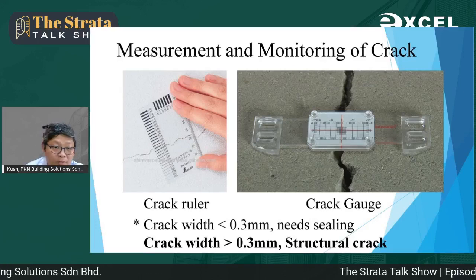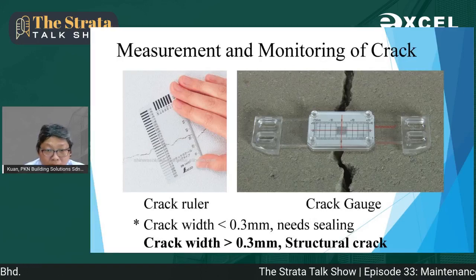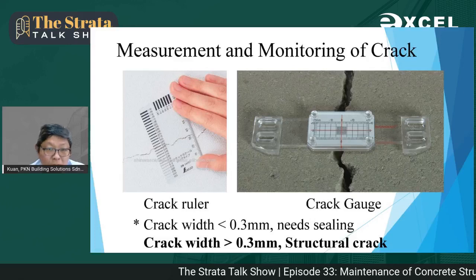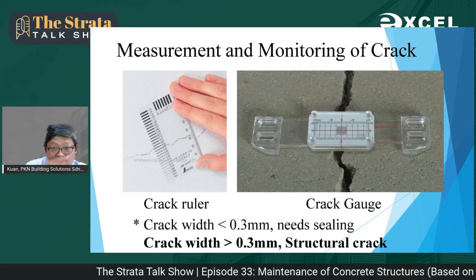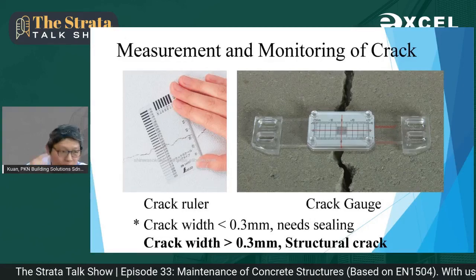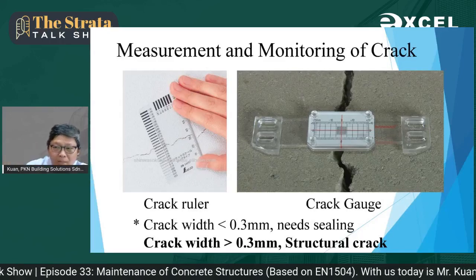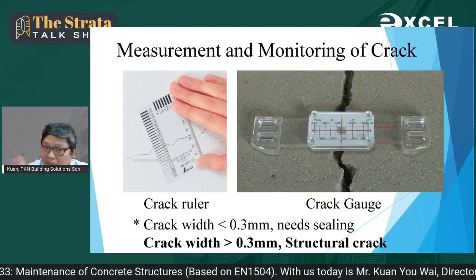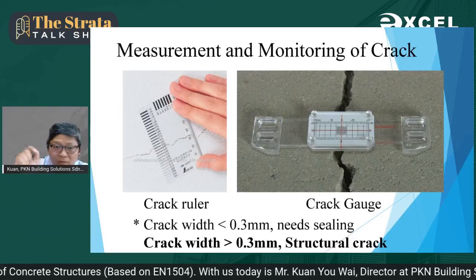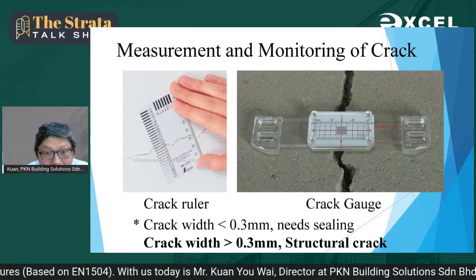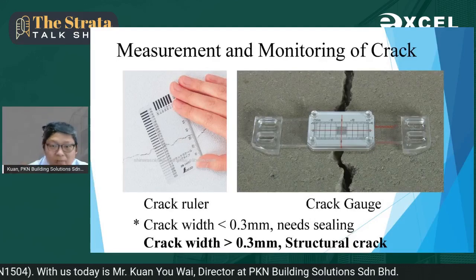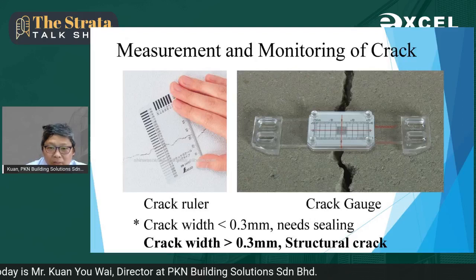First of all, we measure the crack width. Anything more than 0.3 mm on the structural element, not on the surface. I need to remind you that even though we see a pillar, we need to remove the cement screed on the pillar to measure the crack on the concrete itself, not the cement screed. So this is something that we need to be aware of.